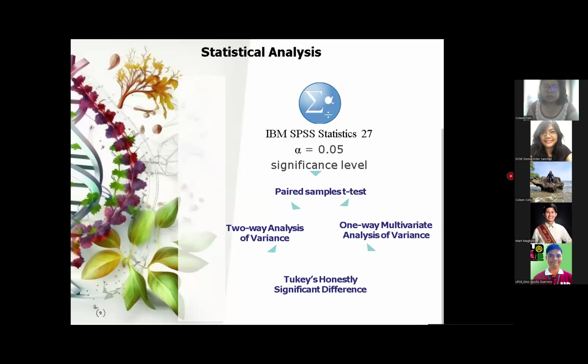So this is the statistical analysis that was performed, using IBM SPSS Statistics. Everything is calculated at 0.05 significance level, except for the follow-up ANOVAs of the MANOVA, which, depending on the literature, following the Bonferroni method, should be 0.025 significance because it is under MANOVA. That is the only one with a different significance level; all the others are 0.05.